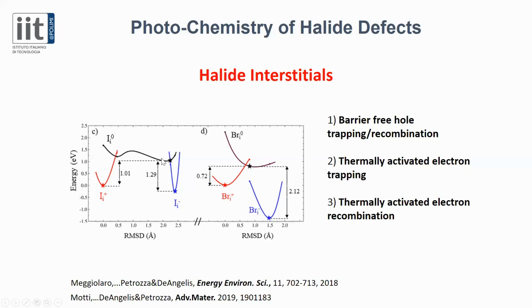And to release the electron back, so for the electron to recombine with holes, we need to overcome another energy barrier. So this means that we have a thermally activated electron trapping and a very long lifetime of the electron. On the other side, the trapping of holes, and so the recombination of holes, is very fast because it doesn't see any energy barrier. So this is what theory is predicting.